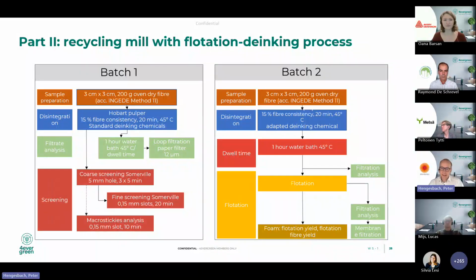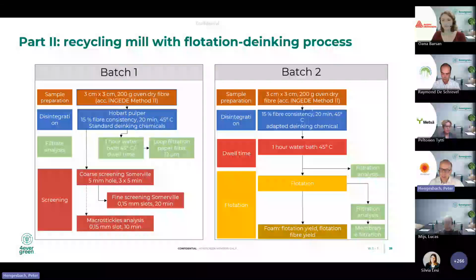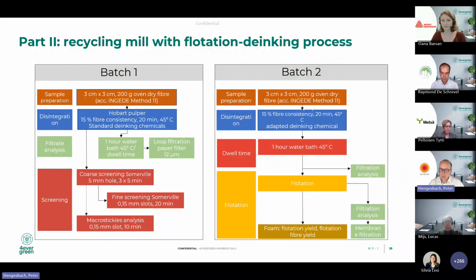What you can see on the left side is the repulping process, just with different conditions, as you have for the conventional process. Here we are adding chemicals using a high consistency pulper. After the repulping stage and some water analysis, we are also performing a screening procedure, which is based on the experience and the application that we have for the conventional process. Quite similar. What is specific in batch 2 is that after this repulping, the disintegration stage, we have a flotation stage after a dilution. We run this procedure to evaluate the quality of the pulp. How well can we remove the ink and hydrophobic particles from the process? This is the core element that is specific to the flotation deinking process.